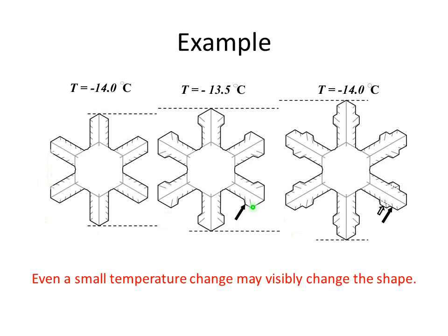The branch slows down, so it gets a little wider. And then it falls back into its original temperature, -14. The branch speeds up, gets a little narrower, but it leaves behind this little wider section, a little knuckle there. It's a permanent feature that's added to the crystal from just a small temperature change.